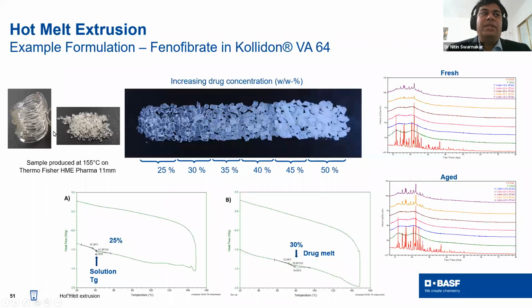Then you can see here, this is extruded as such, then pelletized with the drug, and they are becoming more opaque. At 25%, you can see it's kind of cloudy. Then when you do the various characterization tools, in the DSC with 25% we observe only one Tg, because this drug has a low melting point around 75 degrees centigrade. If you're getting a Tg, it means there is no melting. It's just a shift in the overall baseline. So here you obtain the Tg in the DSC curve. DSC is differential scanning calorimetry. If you observe Tg, it means it's not in crystalline form.